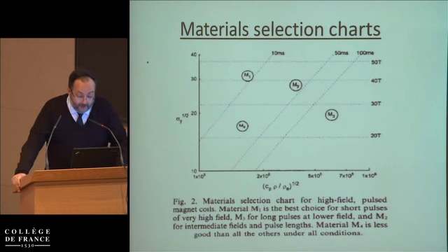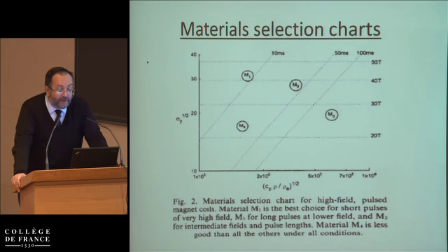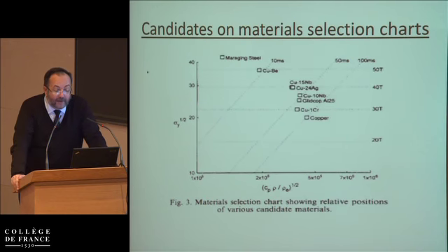Now, if you look at the material selection charts, which would be on one side the yield stress, on the other side the combination of electrical conductivity, density, and thermal capacity, you will have here the requirements for various Teslas, various fields you want to reach, and various durations of the pulse. Now, here are the candidate materials that you have on these selection maps, and these materials are very often copper-based, either pure copper, or copper reinforced with beryllium, or copper reinforced with niobium, with silver. Pure copper is very good for resistivity, but not good for strength. The maraging steel would be very good for strength, but not very good for resistivity. And again, you have to pay a contradiction between the properties.